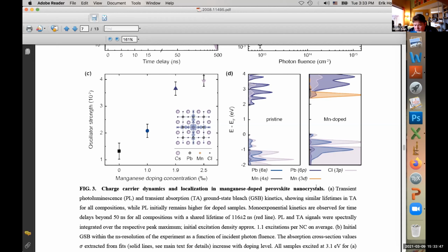One of the potential reasons is that DFT is single configuration; maybe there are some additional tweaks with functionals. But it is quite clear that this manganese-doped system must have occupied and unoccupied levels inside the forbidden band, inside the band gap. And here, in this last panel, the unoccupied manganese overlaps with the host matrix, this yellow. In the valence band, I think there is a little sub-peak, but it is not at the frontier, it is lower in the occupied region. We either do not see it, or it completely overlaps with the host matrix, while it should be a similar yellow peak above the valence band. I see.